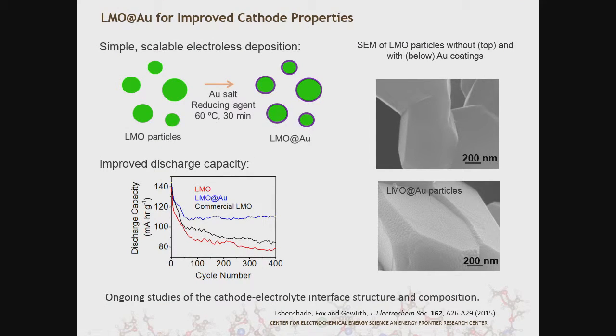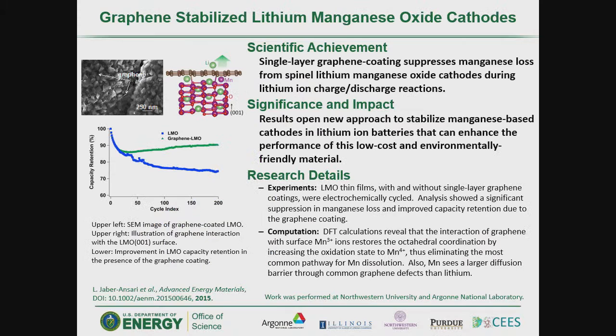Andy Gewirth took a completely different approach, doing electroless deposition of gold on LMO. These are SEM images without and with the gold particles, and what you can see is when you do the cycling, with the gold coatings you get a substantial improvement of the capacity retention over a large number of cycles. A completely different approach, but nevertheless effective in reducing the capacity fade in these materials.